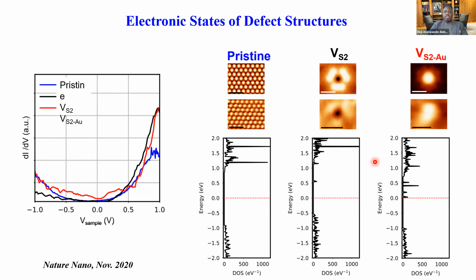Yes, if the effect is there, if a gold atom is adsorbed, you can definitely and 100% of the time recover the gold. And this effect, we only see it in defective areas. In the pristine areas, hundreds of measurements, you will not see the memory effect. So you need a defect, and you need a metal ion adsorbed into the defect to get this memory effect.